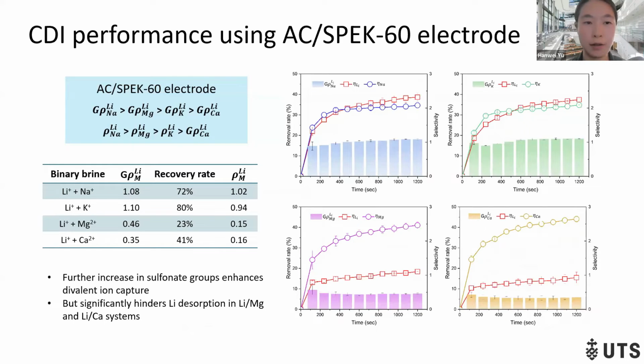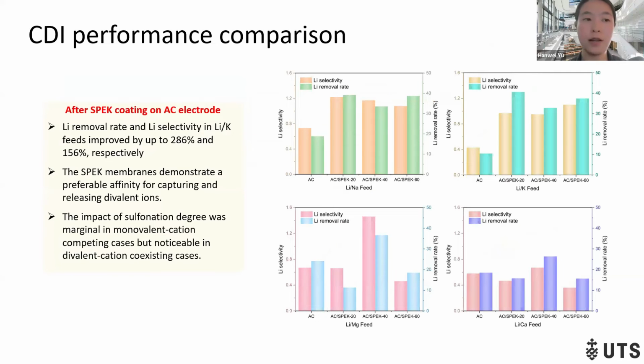This is the result using the AC/SPEK-60 electrodes. The increase in sulfonate group enhanced the divalent ion capture, but significantly hindered lithium desorption in the divalent cases. So here is a comparison of CDI performance among SPK 20, 40, and 60.